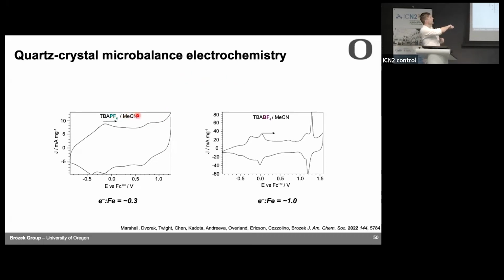So we plot the current in PF6 versus BF4. It looks like what I showed you before. We can count up the charge. When we use the bigger PF6, you oxidize about 1/3 of the iron sites. When you use the smaller BF4, you oxidize about all of the iron sites, so it gets easier.